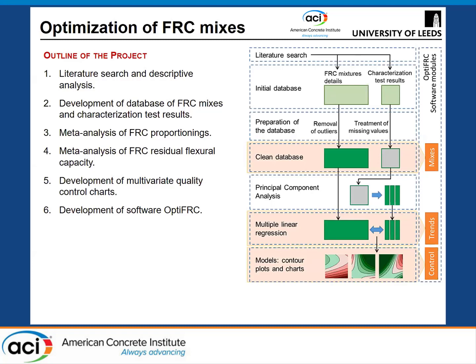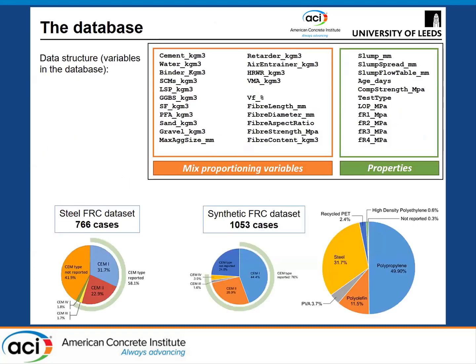So the database that has been collected for this project has been organized as different variables in parallel. So we have some variables that I call the mixed proportioning variables, which are like the cement content or the superplasticizer, the type of fibers, the fiber content, length, diameter. So those are properties that define not only the relative amount of the different constituents of the mix, but also their main descriptors. What is, for example, the maximum aggregate size? What is the length and aspect ratio of the fibers? What is the type of SCM that you have in a certain mix? All those are mixed proportioning variables.